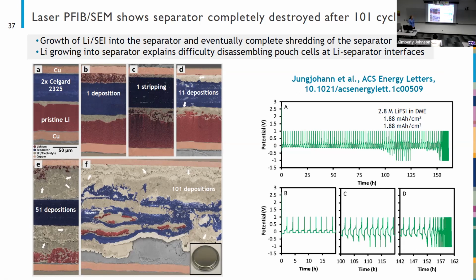And then by 101 depositions, we know the cell has failed. We're no longer able to deliver capacity, but we also see that it's failed very clearly in our imaging. The separator has been completely shredded by the lithium, and now it's just all sort of intermixed and intertwined. And so this is not good. This is not what we want.